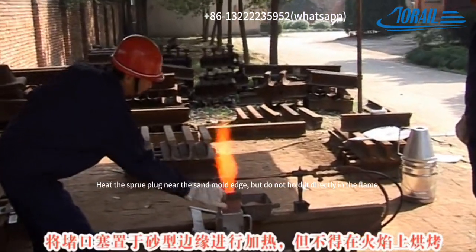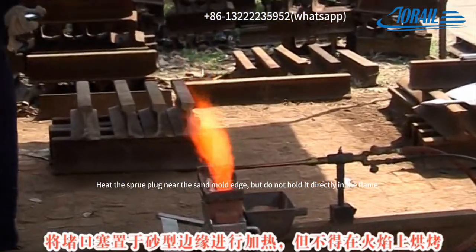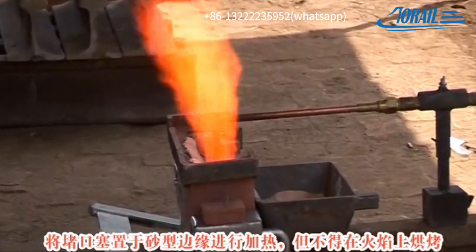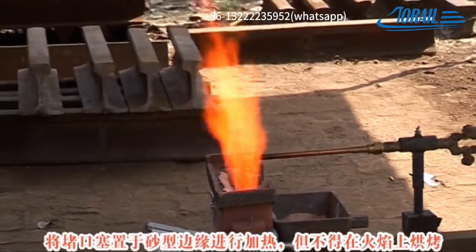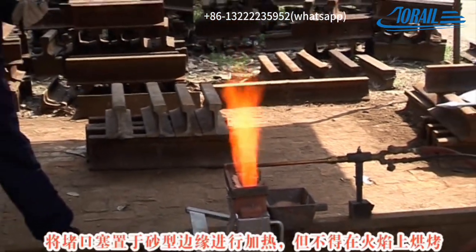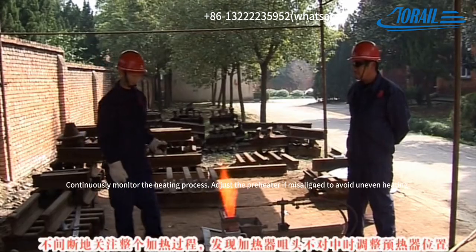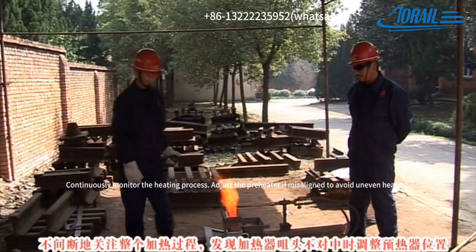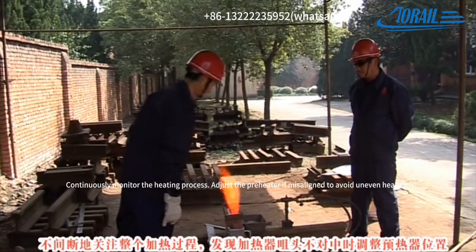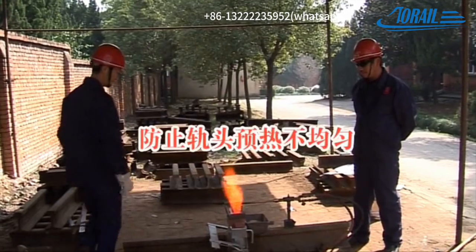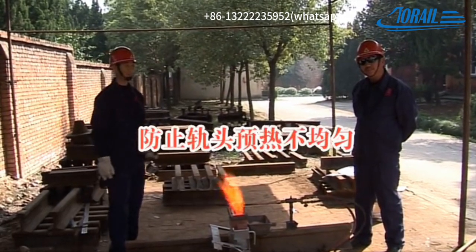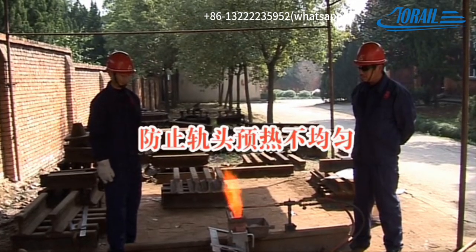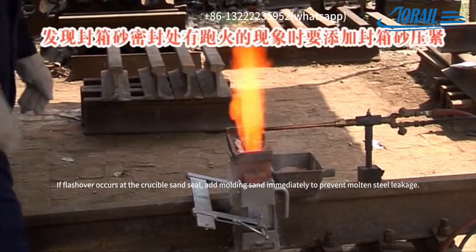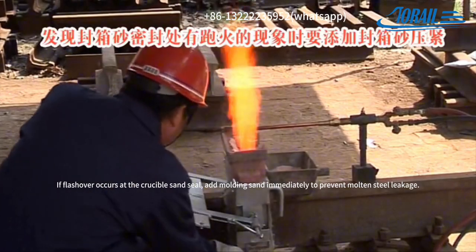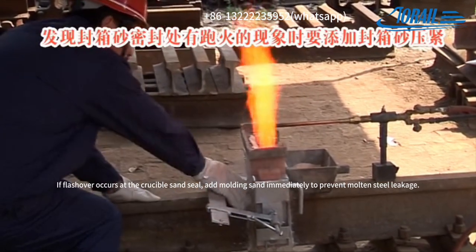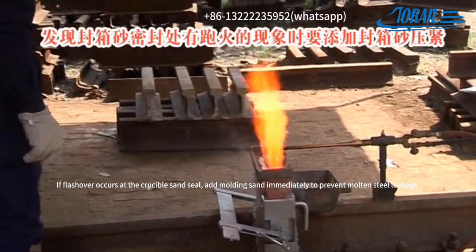Heat the sprue plug near the sand mold edge, but do not hold it directly in the flame. Continuously monitor the heating process. Adjust the preheater if misaligned to avoid uneven heating. If flashover occurs at the crucible sand seal, add molding sand immediately to prevent molten steel leakages.